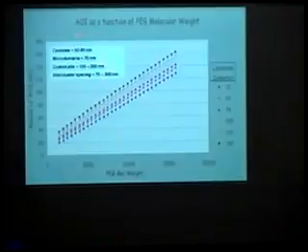These all have dimensions in this 50 to 100, maybe 150 or so nanometer size range, which compares quite nicely with the radius of the area of influence for polymers that are between, shall we say, 2,000 and 5,000 or so in molecular weight, which are the most common ones we're going to use.